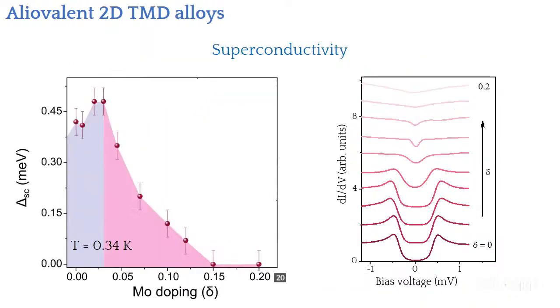So concerning the superconductivity, here's the evolution with the molybdenum doping. Interestingly, the superconducting gap has a tendency to increase at the beginning and then drops. You can see that this gap, for example, is larger than this one or this one. The reason behind it, we believe, is that as you add more and more molybdenum, you reduce the density of states. This material is at the verge of being magnetic. It's very close to being magnetic, but it's not.